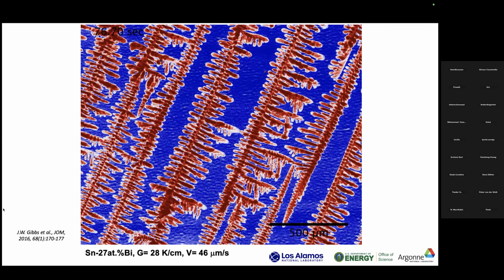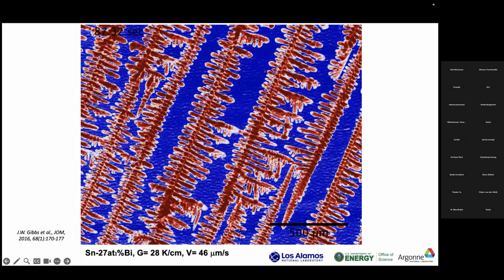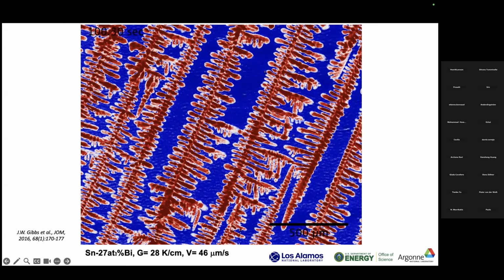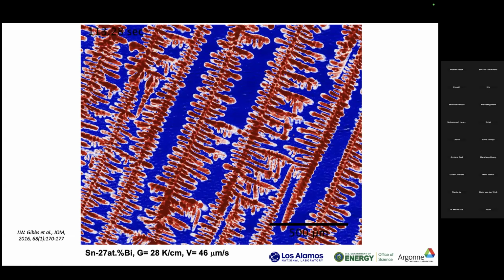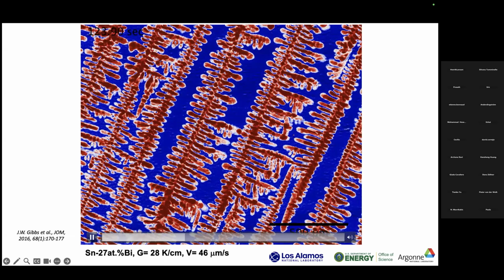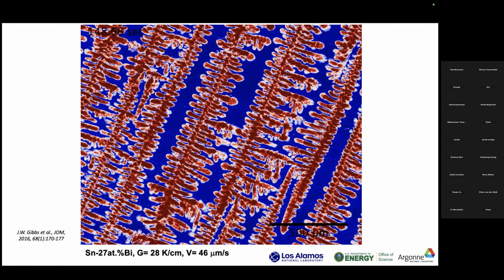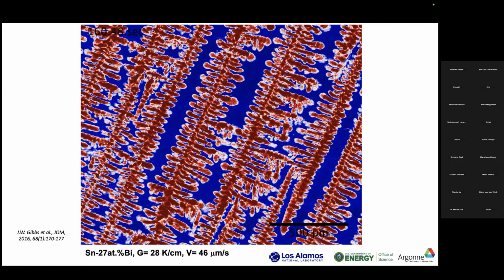And so an important point about this example is this is even a thinner sample. This is thinner than 200 microns. And we see, even in these thin constrained samples, we still see convection in the melt. So why is this important? If I took this to one of my colleagues, like Alain Karma at Northeastern University, and I asked him to do modeling of the microstructure, in the first pass, they likely wouldn't incorporate the convection in the melt.